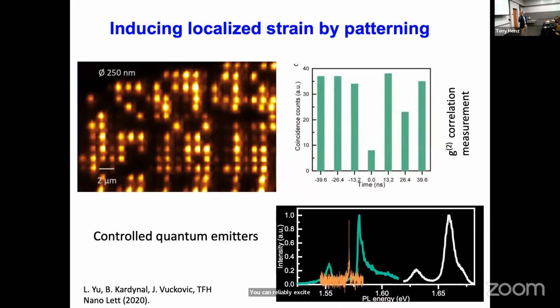It's basically like an atom, but the difference is that this is a quite convenient experimental platform, which could be driven not only by light, but also by electrical excitation. Consequently, that sort of capability is quite interesting. You can also work towards the possibility of having whole arrays of these quantum emitters and looking at their coupling. This is really facilitated by the localization of strain and the control of the placement of the excitons, accessing this very small lateral scale.